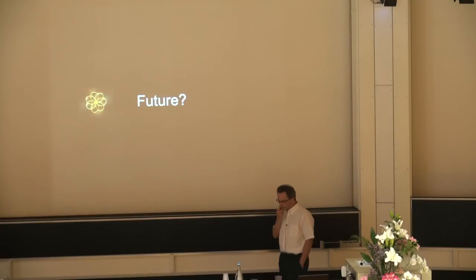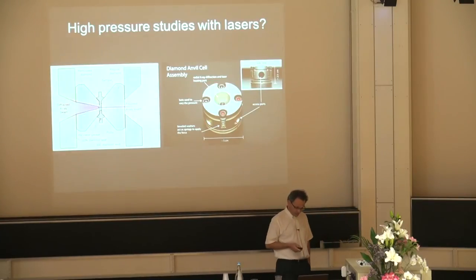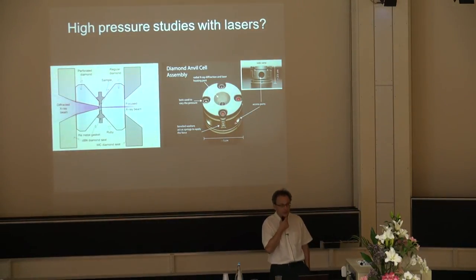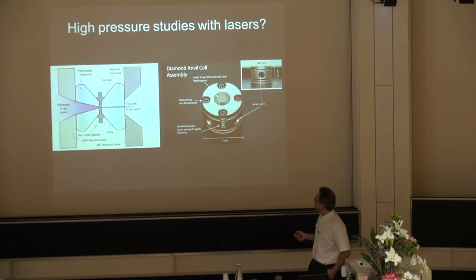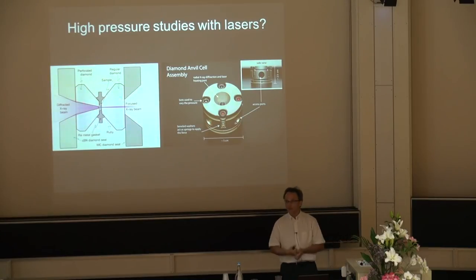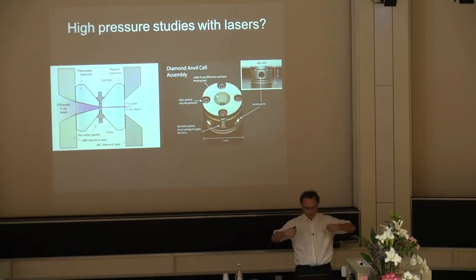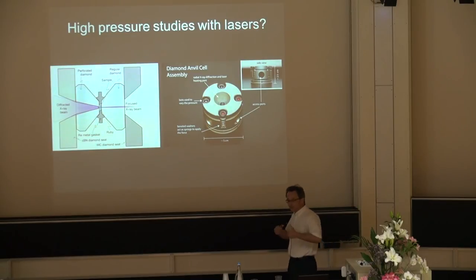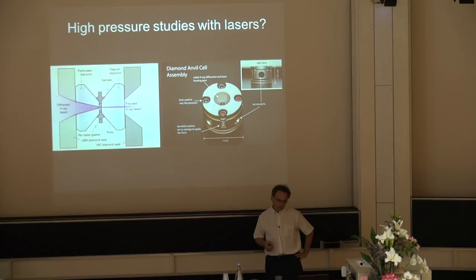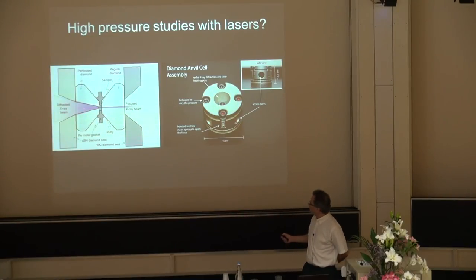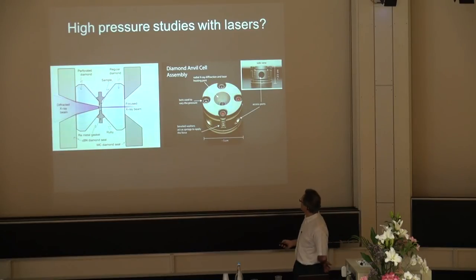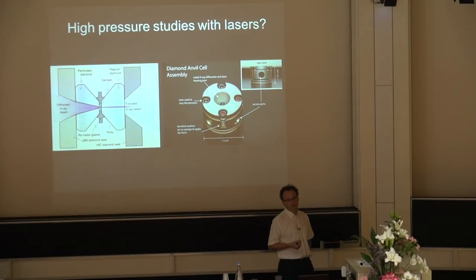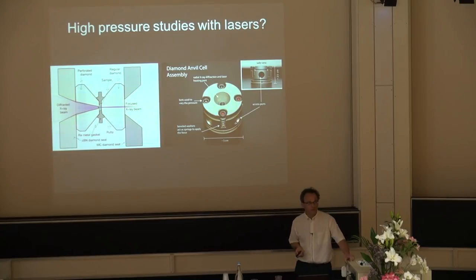But let's say a few words about the future and some of the directions we are exploring. One of them is high-pressure studies with lasers. When we study high-pressure materials, the typical tool I use is two diamond components that you press together. In between, you press given materials you'd like to test under very high stress, very high force, very high pressure. And then after that, you eventually analyze that volume, which is extremely small. So this works fine, but of course you are testing extremely small volumes of material. So it's interesting for fundamental studies, but you cannot do much with that.